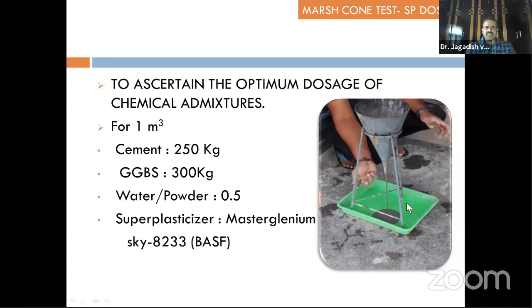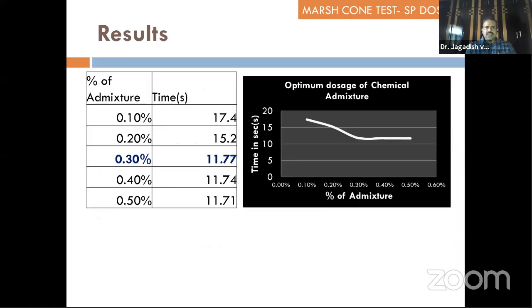This is the typical mix. When we add 0.1% of admixture, flow time is 17 seconds; 0.2, 15 seconds; 0.3, 11 seconds. After 0.3, at 0.4 and 0.5, it is giving the same seconds. So that means 0.3% is the optimum dosage of the chemical admixture. Beyond that, you should not add.